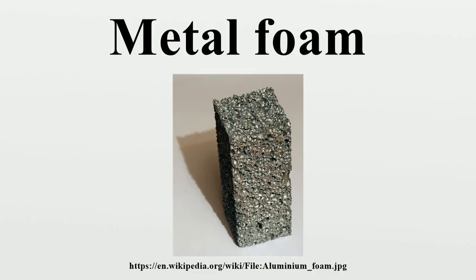Thermal. Tadrist and Al listed several criteria to assess a foam in a heat exchanger. The comparison of thermal performance of metal foams with materials conventionally used in the intensification of heat exchange first shows that the pressure losses caused by foams are much more important than with conventional fins, yet are significantly lower than those of the bed of beads. The exchange coefficients are close to beds of balls and are well above the blades. Foams offer other interesting features, thermophysically and mechanically. Very low mass, large exchange surface, relatively high permeability, relatively high effective thermal conductivities, good resistance to thermal shocks, high pressures, high temperatures, moisture, wear and thermal cycling, good absorption of mechanical shock and sound. Pore size and porosity can be controlled by the manufacturer.